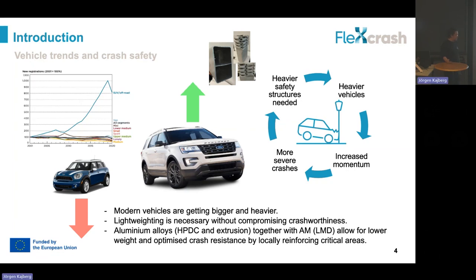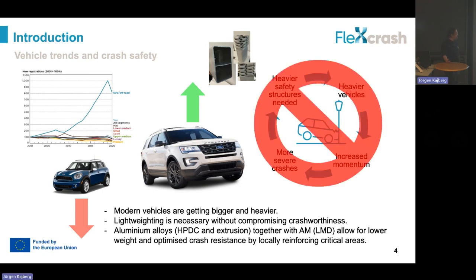And here in the FlexCrash project, we use aluminum alloys, such as high pressure die casting, where you cast large lightweight parts, and extruded aluminum, and then you can use additive manufacturing to allow for low weight and optimize crash resistance by locally reinforcing critical areas. So basically, we want to break that cycle. We don't want to increase the weight, but we want to have better crash safety in our vehicles.